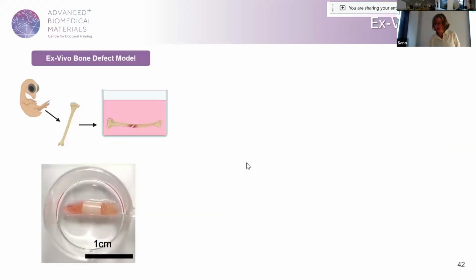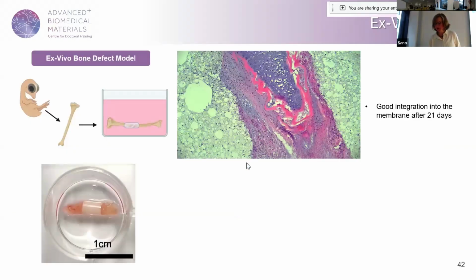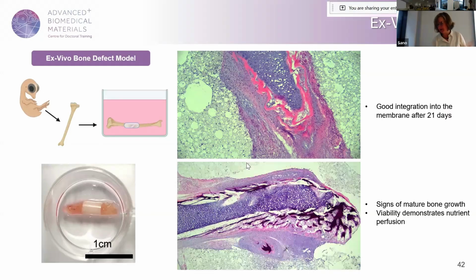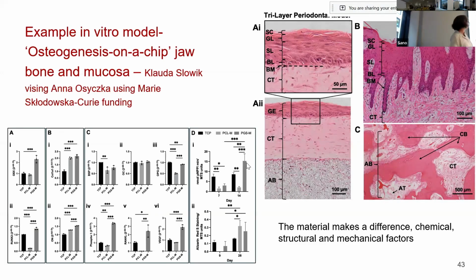And then we can use an ex vivo bone defect from the chicken. So again, because this is such an early stage chicken, it's not an animal experiment. It's before the time when it would be classified as a full animal. And the sample can be wrapped around it, and we can look at bone growth across the defect, which is mimicking a broken bone.